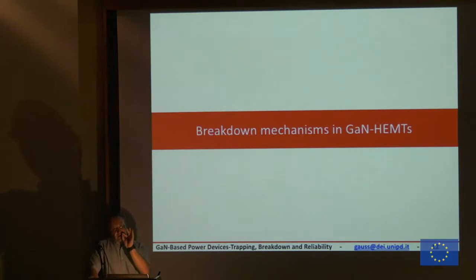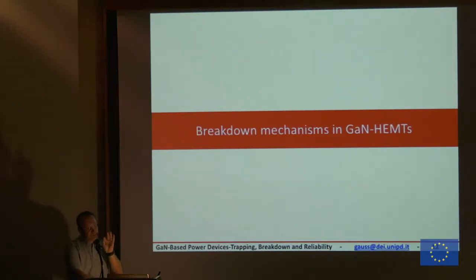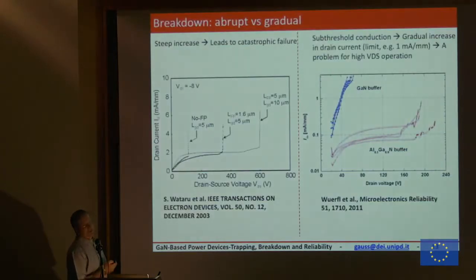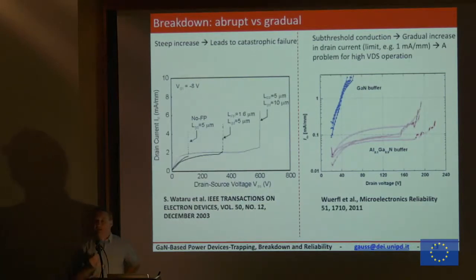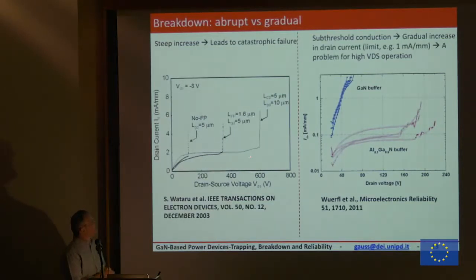Let me also get a little bit into the breakdown issues, because there are some points that are extremely important for the following of my talk. It is the breakdown. The breakdown in gallium nitride has been one of the biggest problems we still face today. The main reason is that the breakdown is abrupt and destructive.